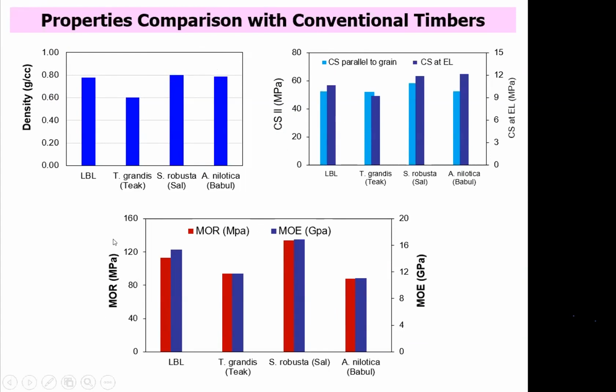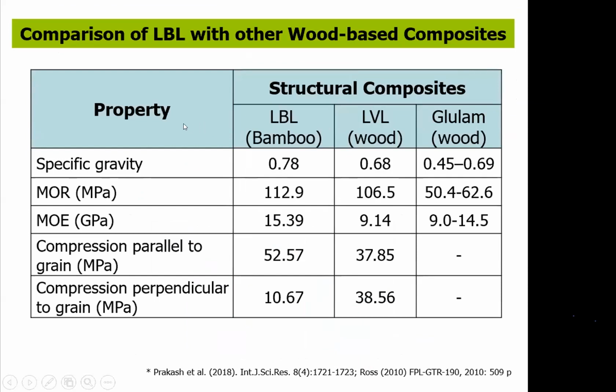Similarly, this is the modulus of rupture, that is bending strength. So we can see that laminated bamboo lumber has a good strength, comparable to different primary timbers. This is the compressive strength parallel to grain. These are some of the properties of laminated bamboo lumber which have been compared with structural wood composites like laminated veneer lumber, and this is glue laminated timber. So these laminated bamboo lumber properties are either comparable or better than the corresponding structural wood composites.